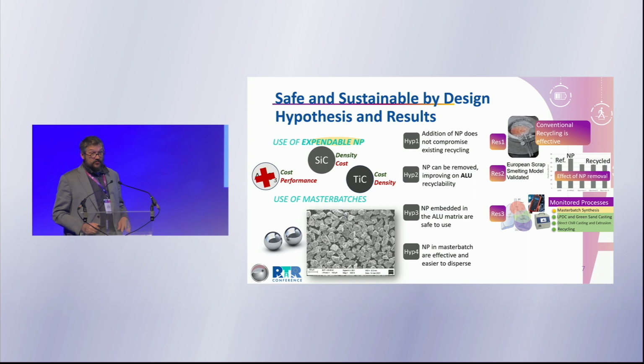As regards safety, we also got good responses, in the sense that we managed to monitor all these steps in which nanoparticles and master batch are used. This is the making of the master batch, the inoculation during casting, the use in LPDC, low pressure die casting, and the use of these master batches in direct chill casting, the extrusion process, and also the recycling process. A partner was there monitoring the release of nanoparticles in each of these processes, and what we saw is basically that there is no difference from the normal practices: the same amount of dustiness and nanoparticles that are monitored in standard processes appears in the processes using the addition of nanoparticles.